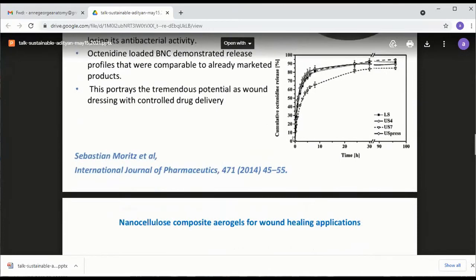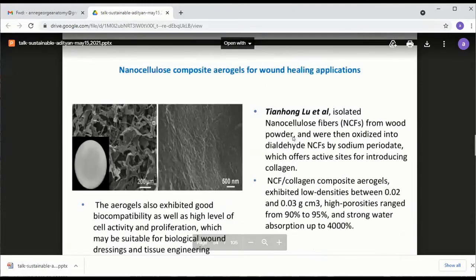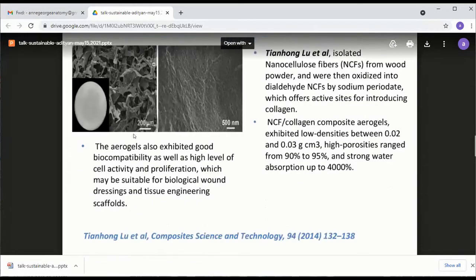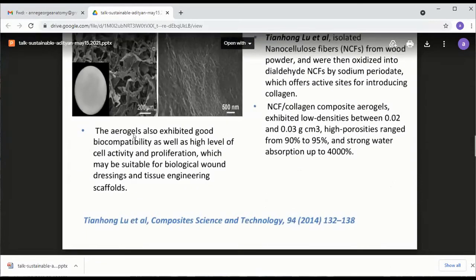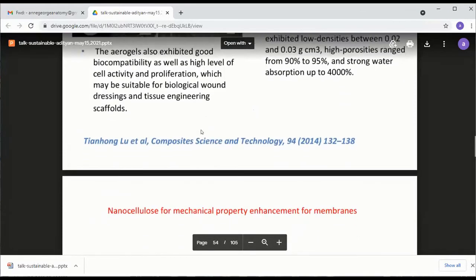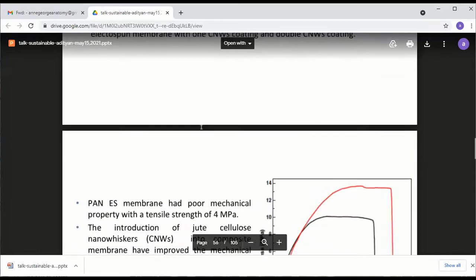Let me show you another example from the work of Tianhong Lu from China. Tianhong Lu and group, you know what they did? They combined nanocellulose and collagen. They made nanocellulose collagen nanocomposites. They made aerogel. You can see the picture of the aerogel. Extremely porous. The porosity is something like 95%. And water holding capacity is 4,000%. And this is an excellent material for wound dressings. You know, it can absorb all the water. Since it's combined with collagen, the biocompatibility is super. Let me show you another interesting slide.